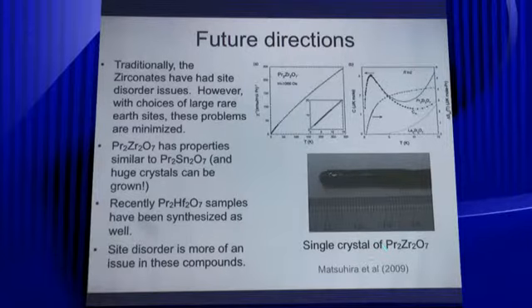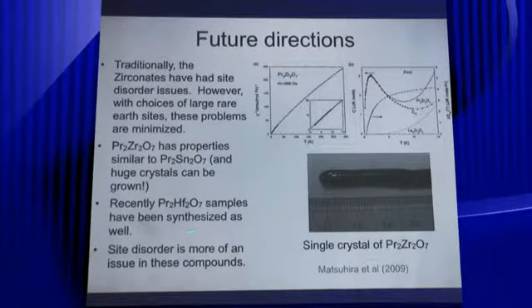So the zirconates show some promise. They're not very stable going across the whole rare earth series. You make it for praseodymium, neodymium, but it starts to get tougher as you go across, and there's a lanthanide contraction that's working against you. You can also look at the hafnate compounds, and there's some preliminary work being done on hafnates, and that's a different problem. It's a financial problem. Hafnium oxide is more expensive than zirconium oxide, but in principle, you should be able to make these compounds as well. But I just want to stress that site disorder is an issue, right?